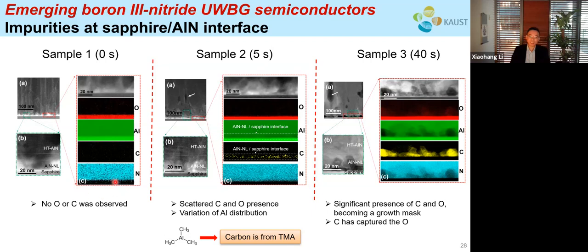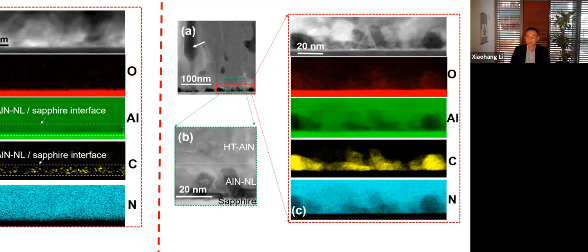For the first sample, we did not see any carbon, right? It is very clean. For the second sample, we start to see scattered carbon as represented by the yellow spots right here. And for the third sample, we see a significant amount of carbon, as you can see here. And also interestingly, the oxygen coexists with carbon, right? You can see they have the same shape. And also this is very significant carbon.